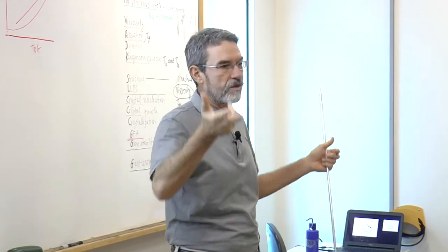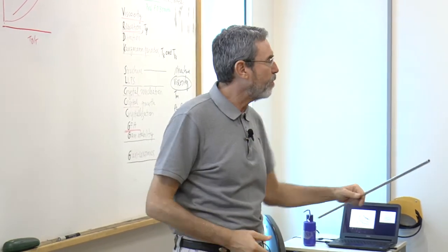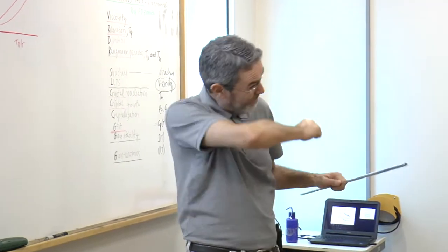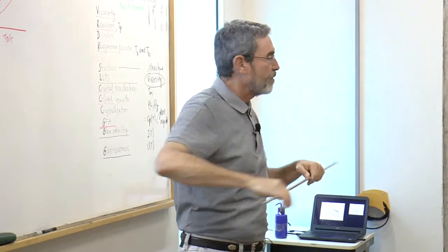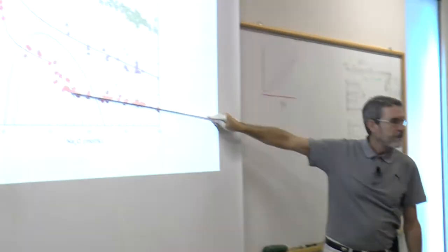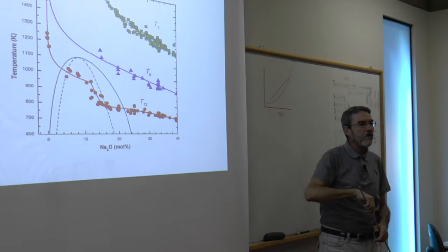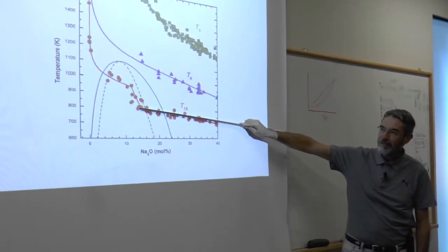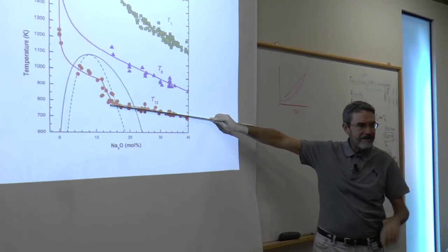This is the scissors effect. You have heard of the scissors effect. You have a chain, a very strong chain. If you cut one link, that's it. So here, we're cutting links of this very strong thing, and we are unjamming the process. Here, it's already completely broken. One or two atoms more, 10% more, makes almost no difference. This is very interesting, and we have to realize this.